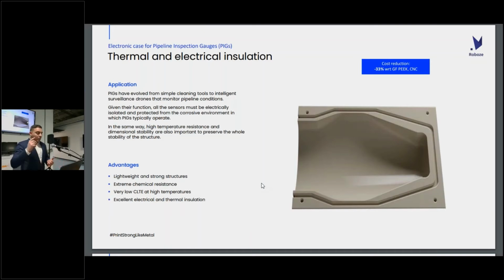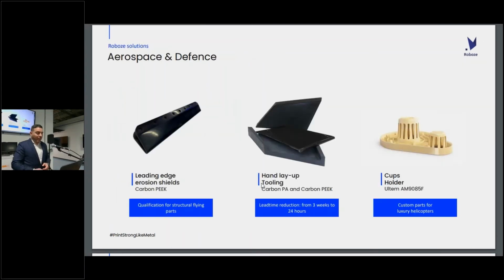So in this case, we built it for a lightweight and strong structure with extreme chemical resistance. This material has the best chemical resistance compatibility with all types of agents, including Skydrol in aerospace. And of course, it has a very low coefficient of thermal expansion at higher temperature. That means the further down I go in the well, the more heat there will be, but the less the material and the part will expand. So ultimately, I have a dimensionally stable gauge for that application.